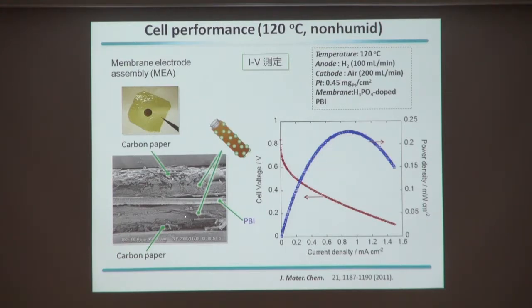Okay, this is just a picture of our MEA membrane, and the same is like this. This is a film with catalyst on both sides, and we measure the performance, IV measurement, cell voltage, current density, and power density were calculated here. It's important to tell that our operation temperature is quite different from conventional. The temperature is 120 centigrade, and we don't use humid air. Instead, just air. So non-humid air is okay for our fuel cell catalyst. And performing in such a unique high temperature condition, our fuel cell reaches this level of power density. This is quite high.